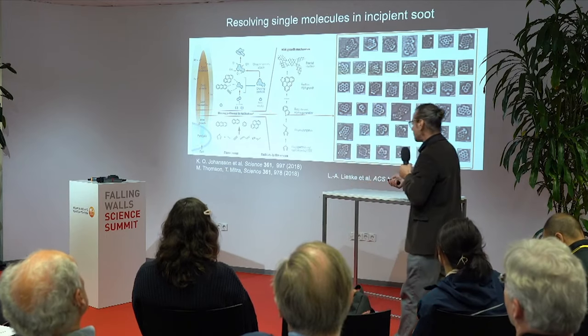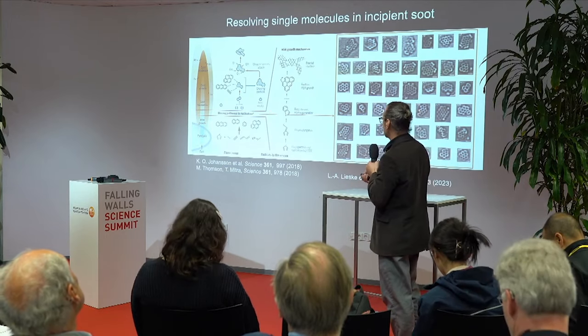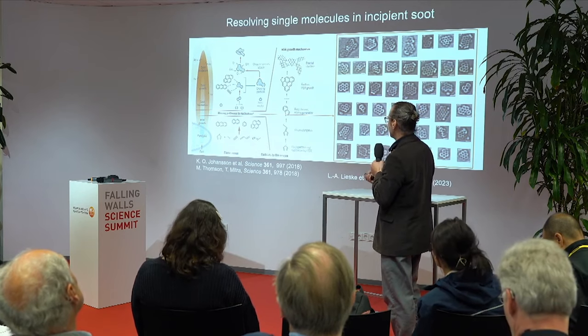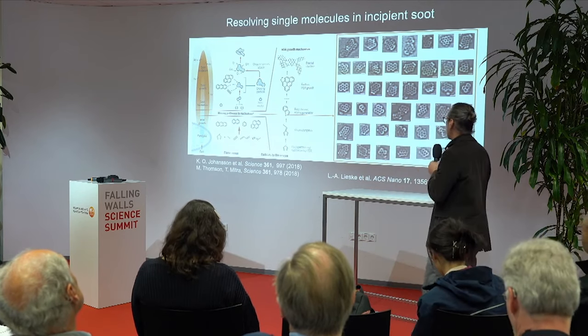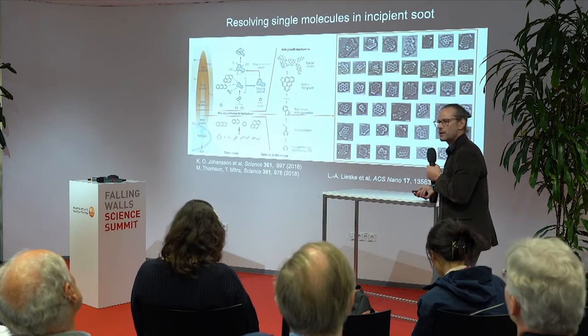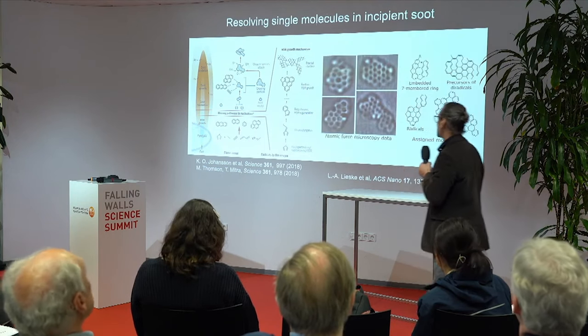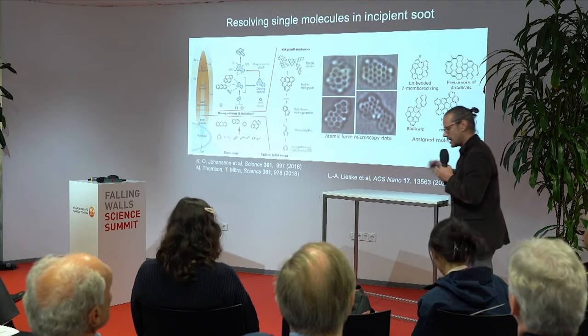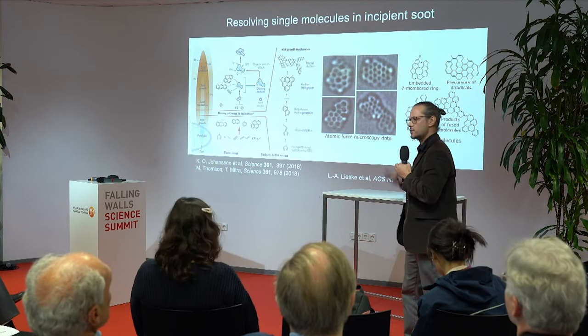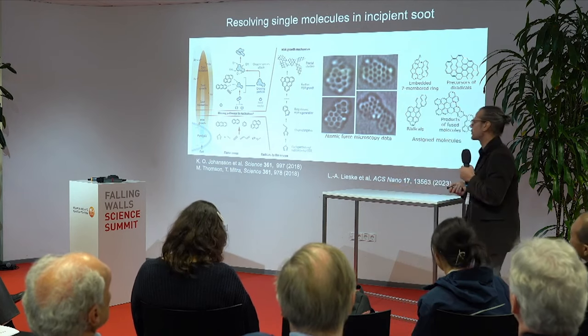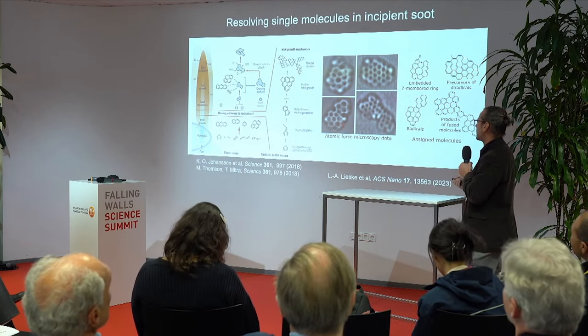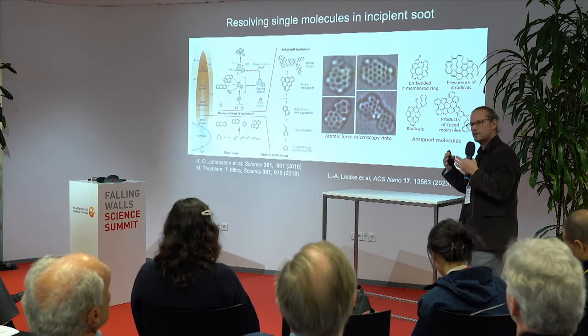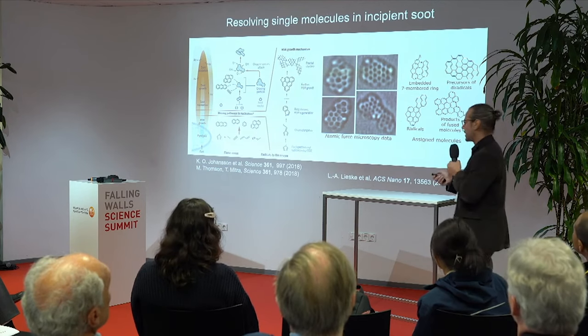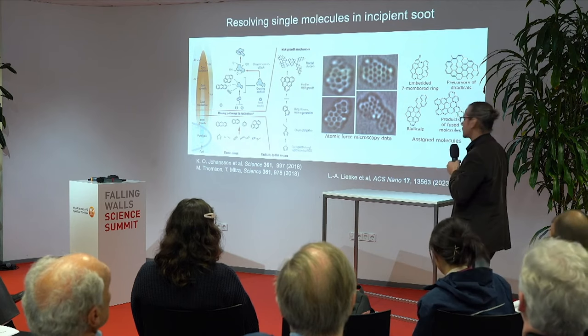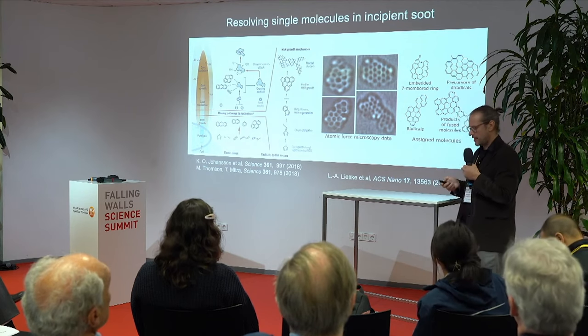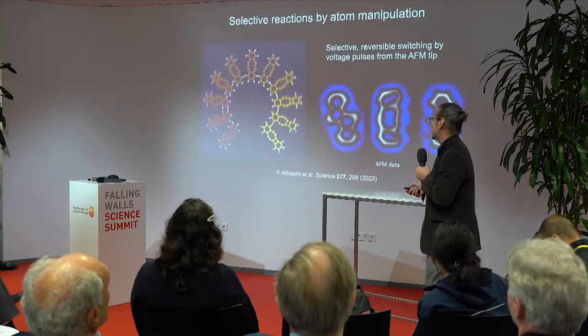And here, this is from another work, showing the question, basically. Here it was proposed that these are pi radicals, and actually this is just a selection of hundreds of molecules that we imaged, and in those we see some that can actually help to explain this nucleation pathway, which was the pressing question of this combustion community. And here you see some pi radicals, so these are very reactive molecules that can form bonds in this flame, and this is already a product of such molecules that had been formed in the flame. So here we use the single molecule sensitivity.